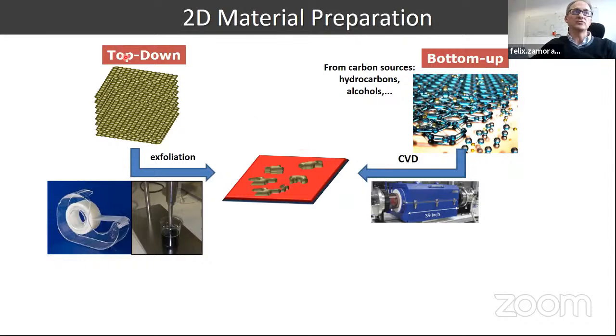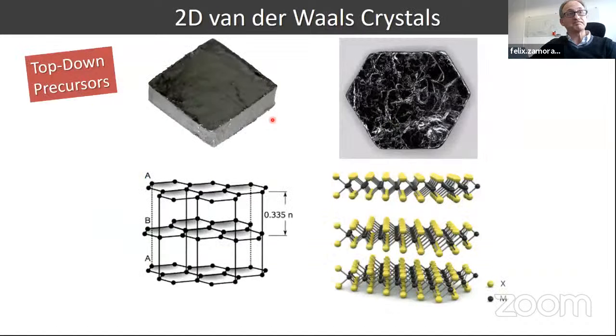But you can also use top-down approaches, where you start with layered 2D material crystals and, by means of exfoliation, you end up with 2D materials. For that, you have to start with precursors, which are indeed the 2D van der Waals crystals. Here I give you two examples. This is the case of graphite, HOPG. The structure of HOPG is represented here. As you can see, we have a weak interaction between layers. If you delaminate these crystals, you end up with a single layer or few layers, and then graphene. It is a similar case for the transition metal dichalcogenides. We have this big crystal, a 2D van der Waals crystal with this structure, and you can delaminate it and end up with few layers or a single layer.